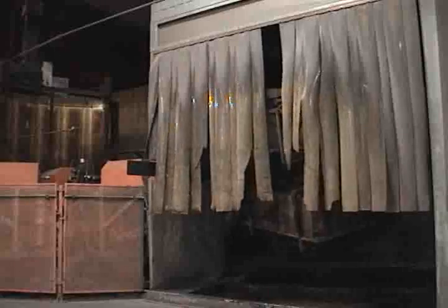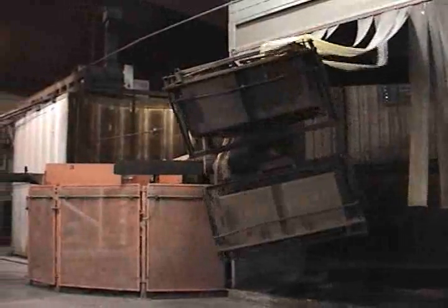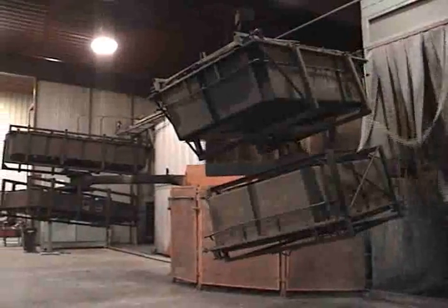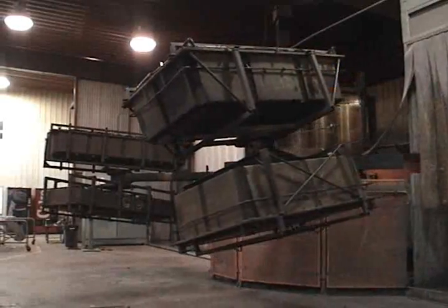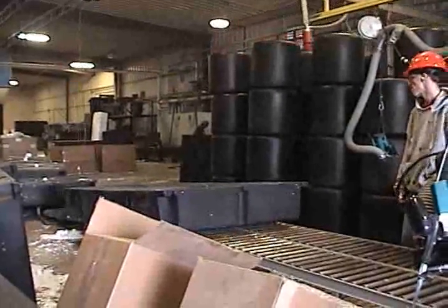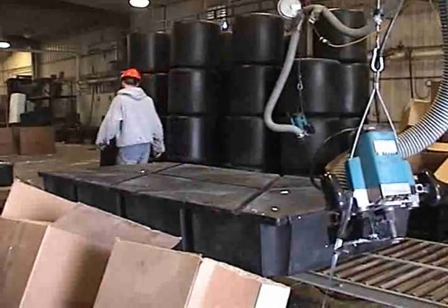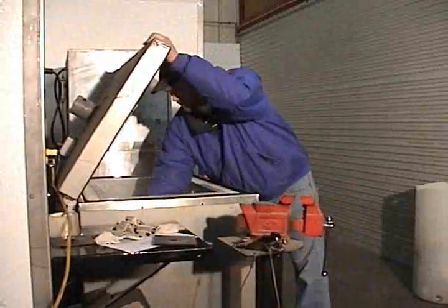And to ensure that no point falls below one-eighth of an inch. If the float fails, it does not ship. As the float sizes and buoyancy capacity increase, the outer wall nominal thickness increases proportionately to maintain the wall strength required for heavy loads and the most difficult dock system environments. A-stock floats' outer shells are properly cured to ensure that there are no air bubbles below the inside third of the wall thickness. If not properly cured, the shells will be weakened, even if they meet the nominal 15 one-hundredths of an inch thickness claimed by all manufacturers. Using less-than-virgin materials can only contribute to this problem. Weak walled floats can fail prematurely.